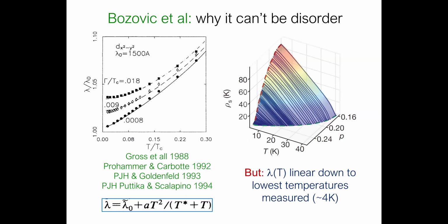Okay, now there's another objection to the disorder explanation, which came from Ivan himself, and that is that the temperature dependence of the superfluid density was linear, as I said before. And it's known for a long time that if you have strong disorder in a D-wave superconductor, the linear penetration depth as a function of temperature crosses over to something that looks like T squared. So a lot of people worked on this in the early 90s, and there's some kind of fit formula that you can use, which tells you something about the width of the impurity band in the system. And it didn't look that way. So Ivan said quite reasonably, this doesn't look like a disorder effect. But he didn't measure down to the lowest temperatures.